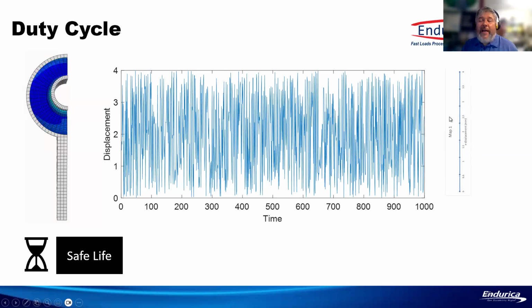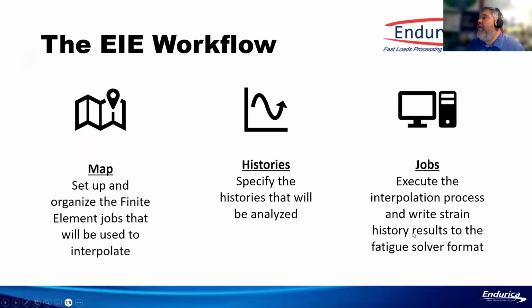So that's what Endurica EIE does. This pre-computed finite element solution, we call the map. So with EIE, you compute a map, and then you can use that to interpolate whatever strain history you've got based on your input displacement history. Now, this example is just one channel of load. EIE can accept maps that have as many as 6 independent input channels. But to keep things simple, we'll just do it on one channel here. And then what EIE does is once it interpolates, for each element, we will get the full time history of the strain, so that we can pass that to the fatigue calculation and get fatigue results.